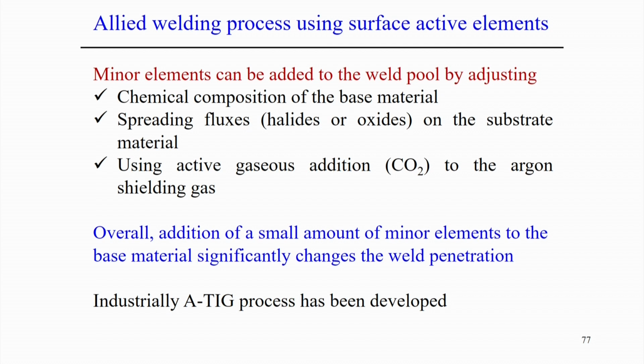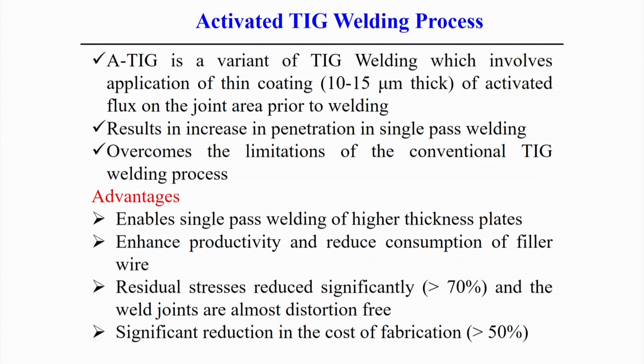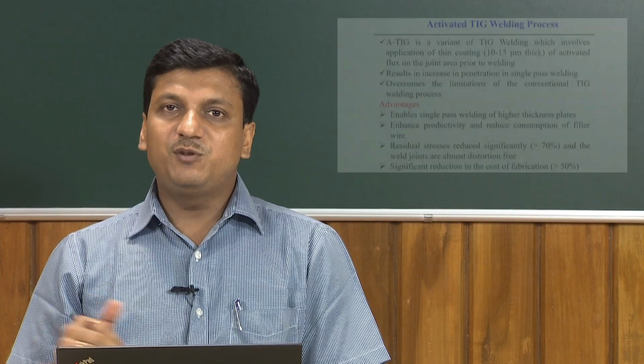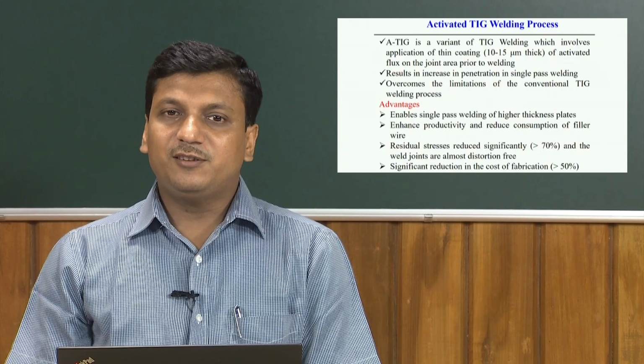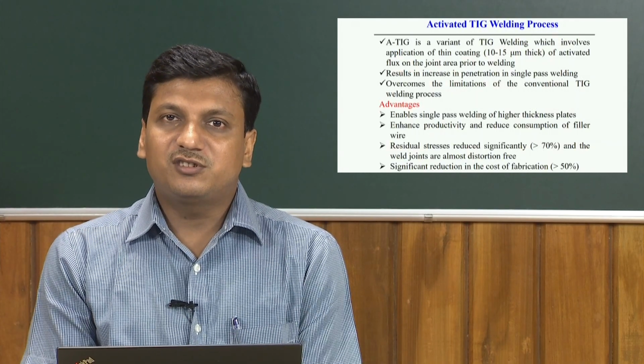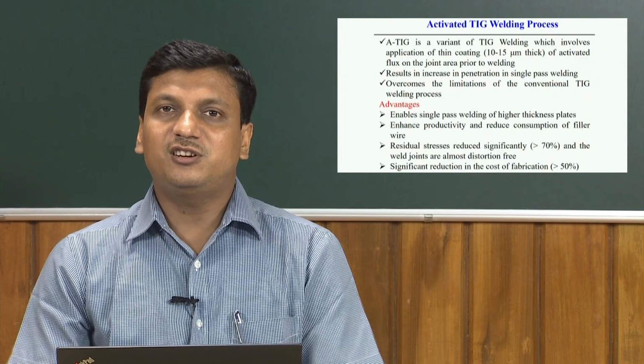There is one development of the process that is called A-TIG, the activated TIG welding process, which has been developed industrially. Activated TIG welding process means activated tungsten inert gas welding process. The A-TIG process can be defined in the following way: A-TIG is simply a variant of the TIG welding process, or we can say the gas tungsten arc welding process. What happens in this process is that a thin coating, 10 to 15 micrometer, of the activated flux is applied specifically on the joint area before welding. Then we can do the normal TIG welding process, tungsten inert gas welding, also called GTAW, gas tungsten arc welding.